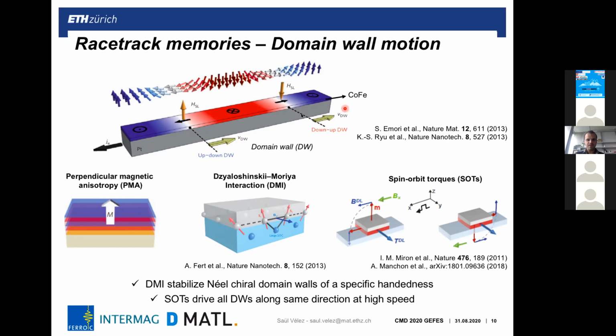brought to the system by using the platinum layer. So the same material that is used for generating spin currents also induces a strong DMI that is capable of stabilizing these domain walls. And importantly, they are chiral because the interaction is set by the material that you bring into the system. So this type of structure allows you to apply charge currents to the material, and then by the spin current generated, exert a torque that is dependent on the chirality of the domain wall, and then drive all the domain walls along the same direction as long as they have the same chirality.